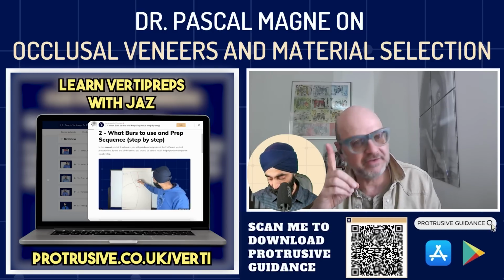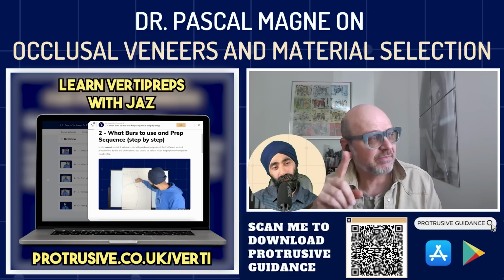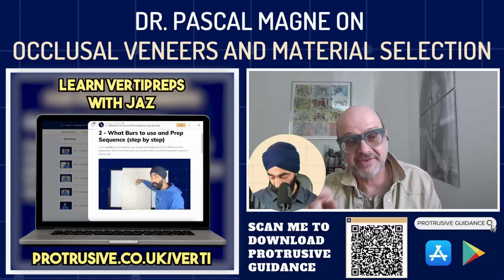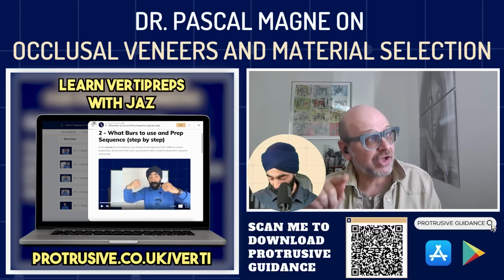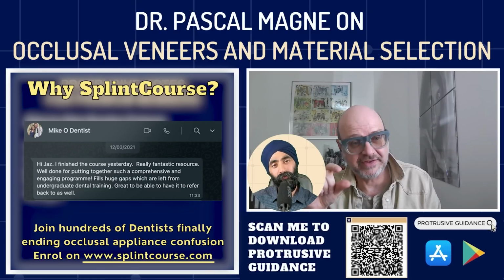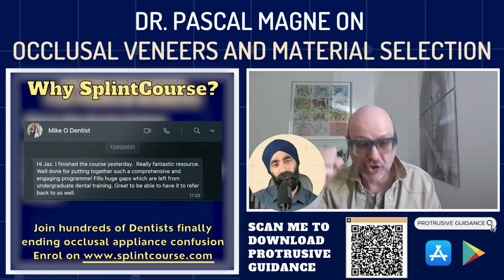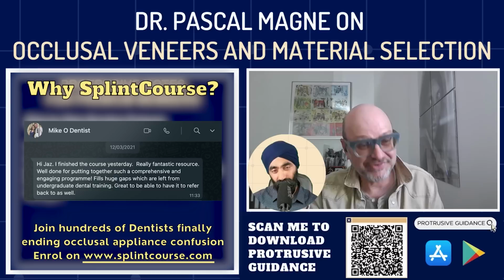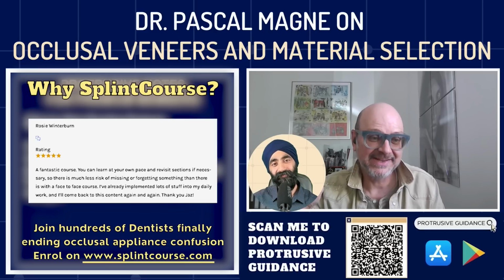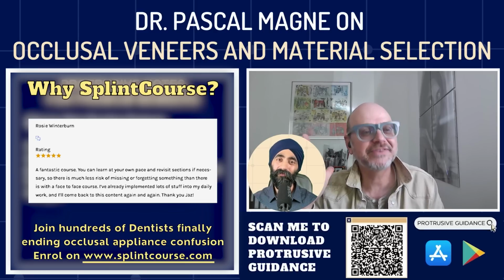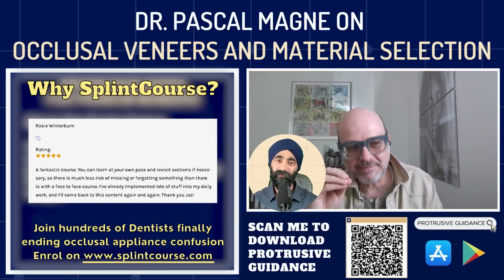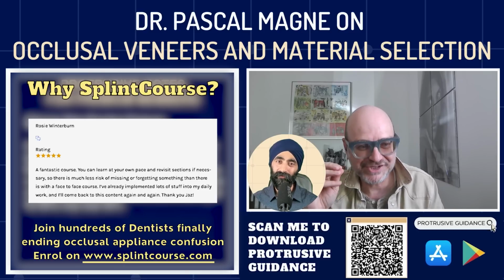Actually, when I said none of the teeth survived, it was wrong. We had with the composite resin onlays, which was Paradigm Z100, a number of teeth survive. And when we took those teeth that survived our very demanding occlusal pounding after the test, and we measured the dentin bond strength, the value was still as it was originally in the unfatigued teeth, which is about 57 to 58 megapascal. Remember, the dentin enamel bond strength, biological bond strength, is around 50, 51 megapascal.